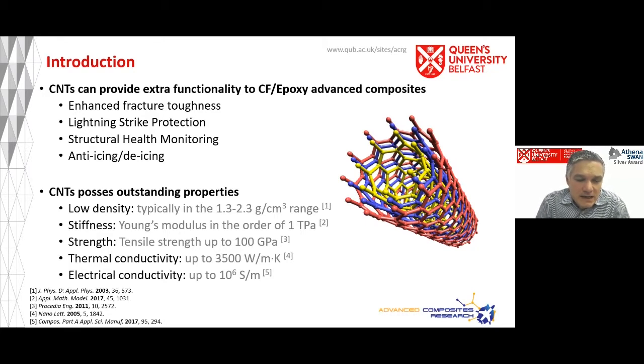And the challenge for us, if you look at some of the outstanding singular properties, they've got very low density, extremely high stiffness, strength. Thermal conductivity is actually higher than, say, diamond. Diamond's about 2,000 watts per meter Kelvin. Silver's only about 400. And electrical conductivity is also very good.